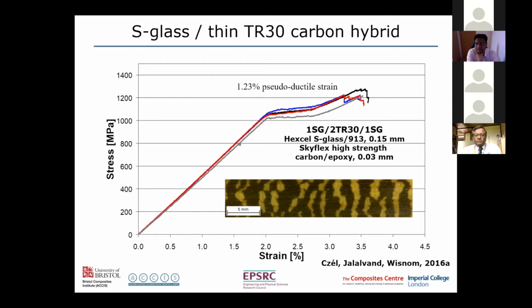So as well as producing these nice pseudo-ductile stress-strain curves, we have an indication that it's been overloaded. And this can be used as a damage sensor, either as part of the surface of the structure or as a separate bonded-on sensor, which could be used indeed with metal structures as well as composites.